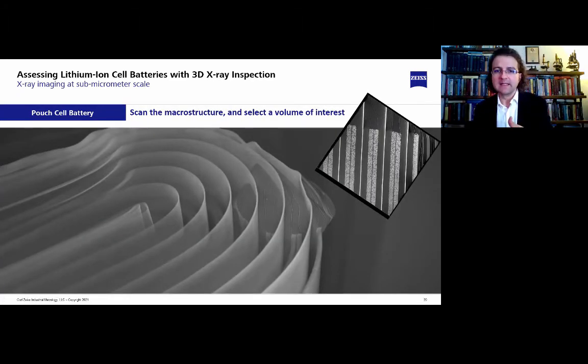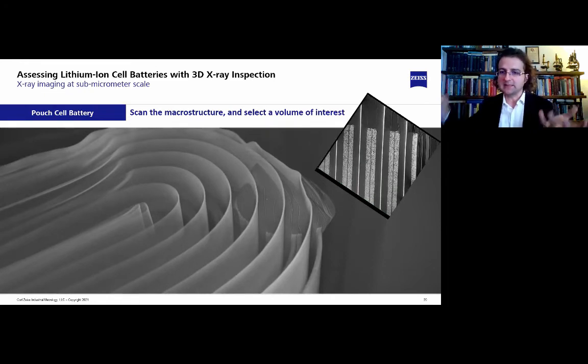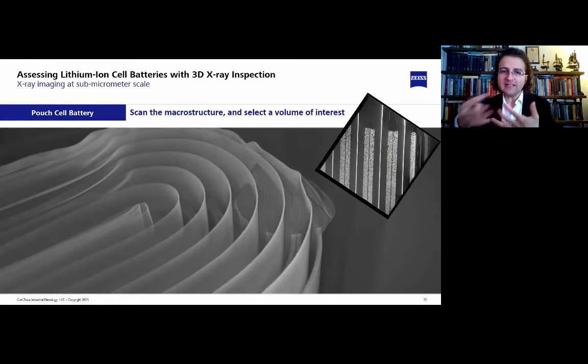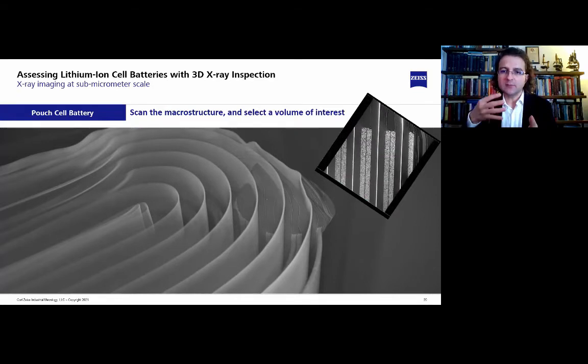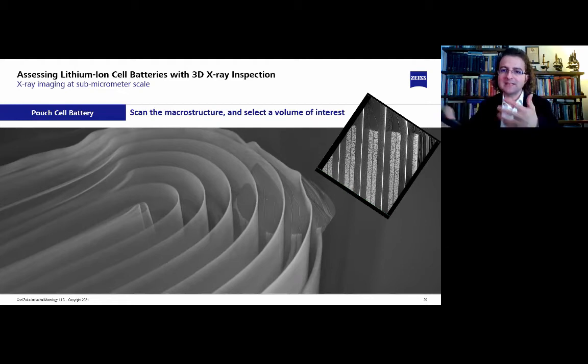Regions of different sections of interest can be selected, as you can see in this image, to see very fine details in the battery without destroying the sample. You can see 2D slices through the 3D cylinder represented in the main image, which can be used to assess, for example, the microstructural changes of cathode material over multiple cycles of charging and discharging the battery. This is important to studying aging effects.